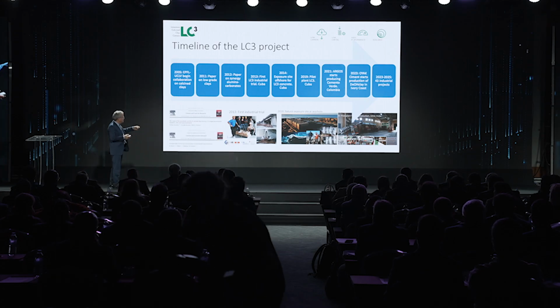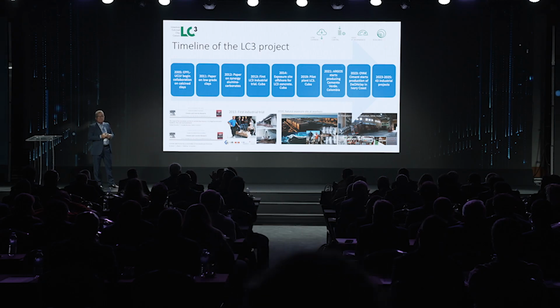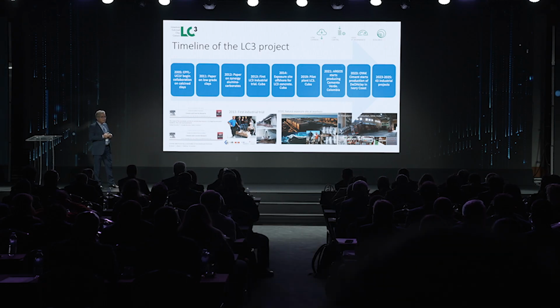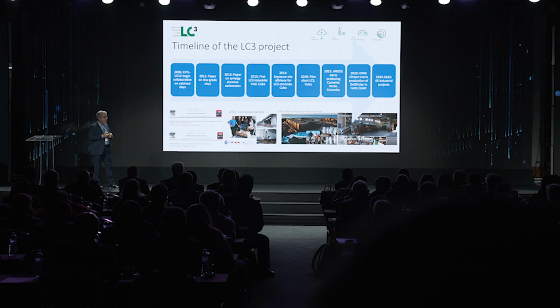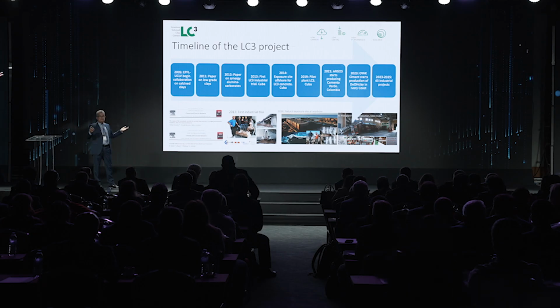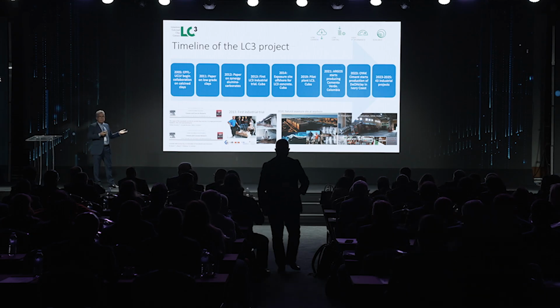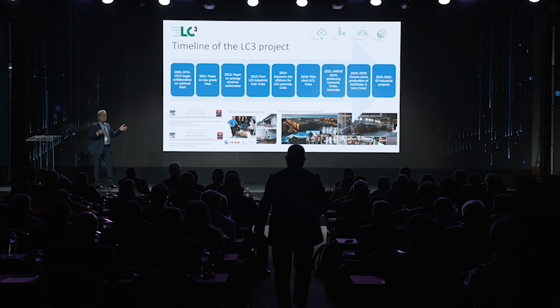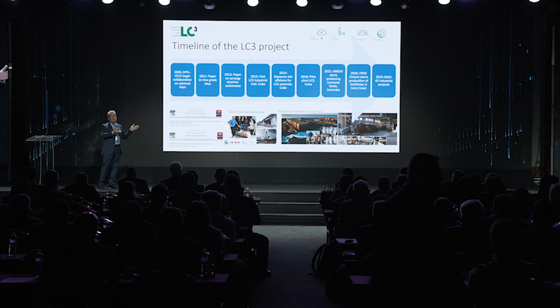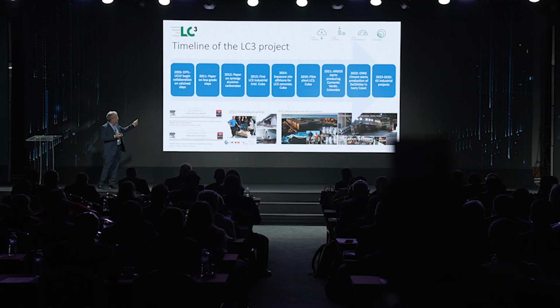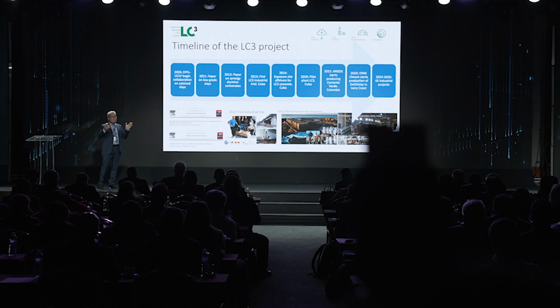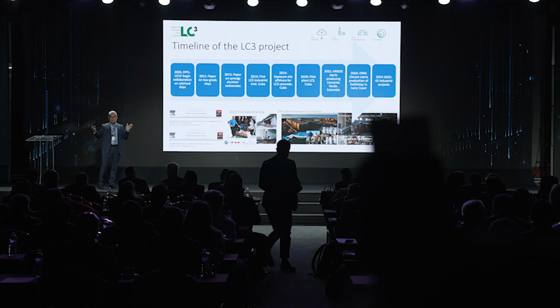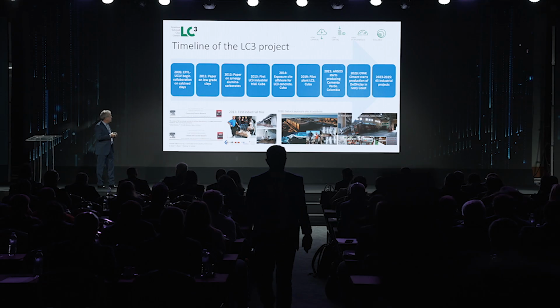We ran the first industrial trial, calcining 400 tons of kaolinitic clay in Cuba, in a very old, outdated plant. We were able to produce around 300 tons of cement, and we were able to massively use the cement. I'm talking about more than 11 years ago now. Because it was a new cement, not in the standards, we were not allowed to use it in commercial buildings, so we decided to put it in blocks. And these blocks were exposed on the seaside, and that has given us the possibility of studying durability, especially in marine conditions, for these elements for many years.